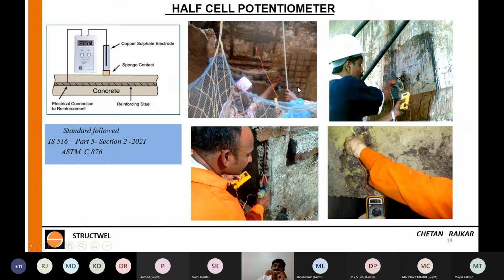Now this particular photo, if you see, you may say, I can obviously see the reinforcement corroded. So why are you doing the test here if you already know that it's corroded? But in any kind of investigation, it is always good to do some tests on good concrete, some tests on suspect concrete, and some tests on obviously bad concrete. What percentage, you would ask me? Maybe 5 or 10% on good concrete, 5 or 10 on obviously bad concrete, and 80 to 90% on suspect concrete. So that you can know what is the acceptance criteria. You have the complete range of good concrete readings, bad concrete readings, and suspect concrete readings.